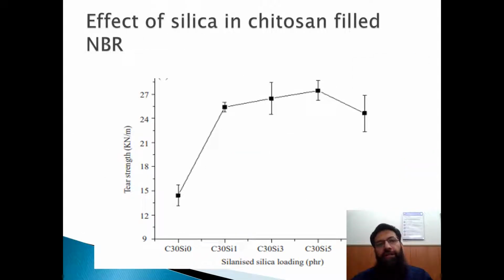We check the effect of the different fillers on the compound of the different polymers and the elastomers. You can see on your screen there is a graph which is showing the effect of the tear strength with the loading of the silica. As we increase the silica loading from 0 to 5 pHr, you can see there is an increase in the tear strength. So up to the 5 pHr loading, and afterwards there is a bit of decline in the tear strength.